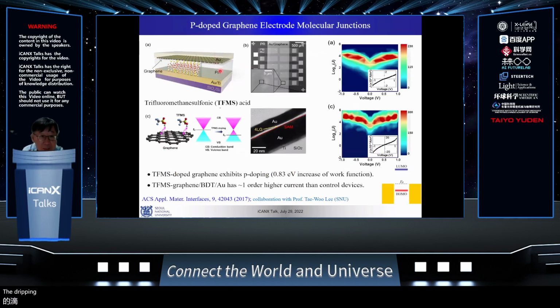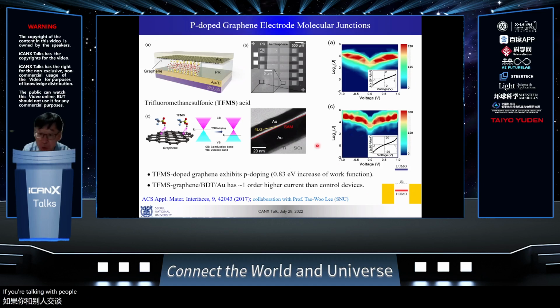The graphene electrode can be chemically doped by applying this so-called molecule on graphene. It withdraws electrons, so it acts as p doping of the graphene, which increases the work function of the graphene. So if you increase the work function, actually this metal level is going down to better match with the HOMO level, which increases the current if you dope the p-type graphene electrode. So that's what we see: before the graphene doping, and after graphene doping the current is higher.